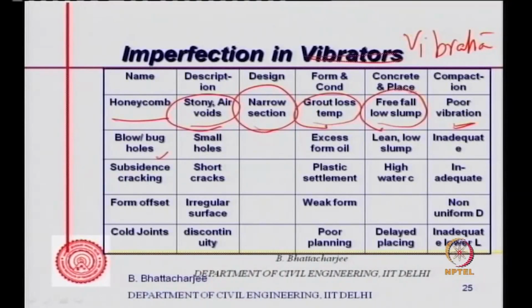Well, blow holes or bug holes, which you see normally in concrete, are small holes, aesthetically ugly looking. Excess form oil, if you are using, can cause this kind of thing. Lean and low slump concrete, you get it, and of course inadequate vibration. So poor vibration can result in honeycombing. Inadequate vibration can increase the bug holes formation. Bug holes are pretty common, they are not very harmful, but they look very ugly. Not a good finish. Subsidence and cracking, of course, this can happen due to plastic settlement.